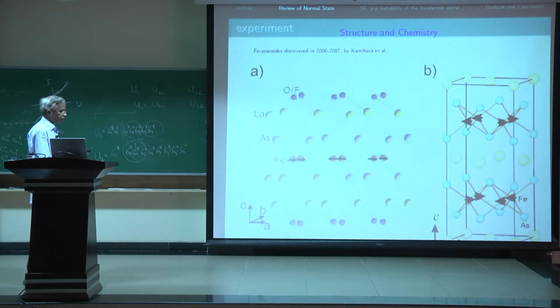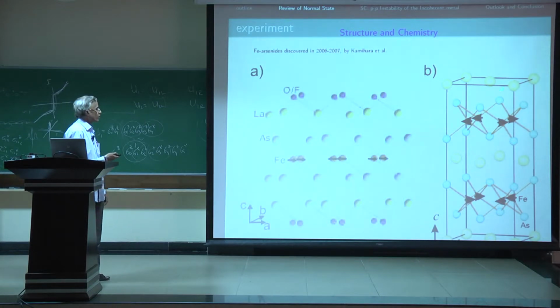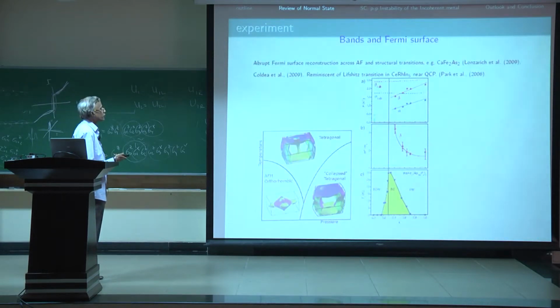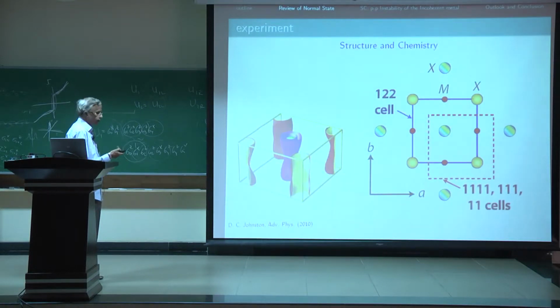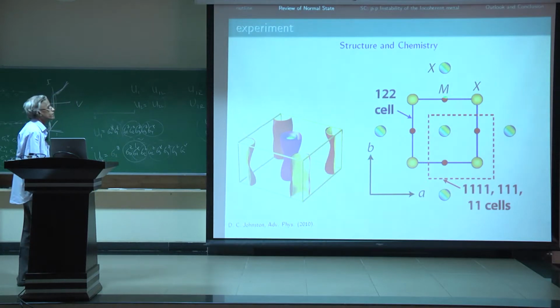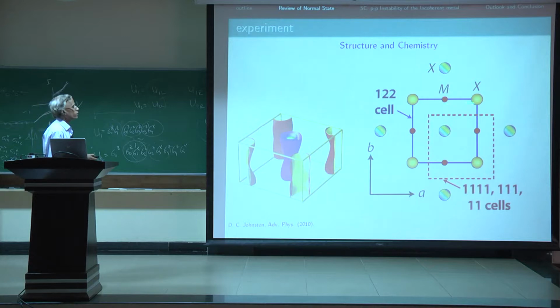So one thing before I proceed is that the kind of antiferromagnetism one observes here is stripe antiferromagnetic ordering, with ferromagnetic ordering along B and antiferromagnetic along A. That occurs due to the fact that if you look at the quantum chemistry in iron arsenides, the hopping between iron d states occurs via intervening arsenic, which lies either slightly above this plane or below this plane in a kind of staggered way.